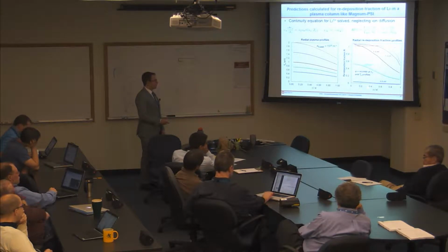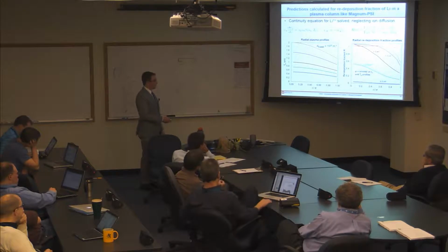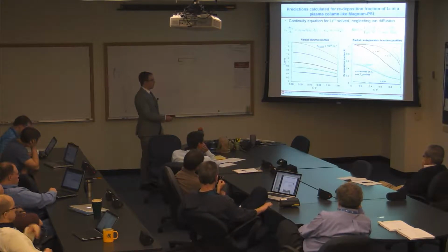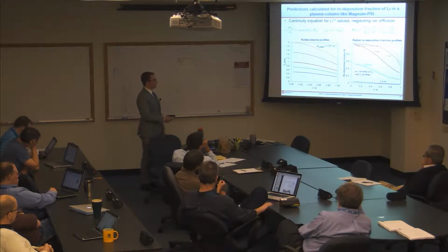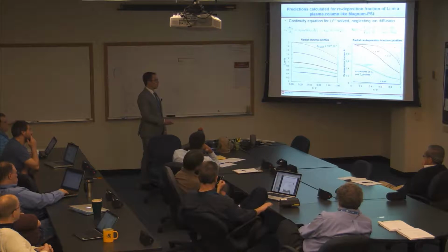And for a temperature of half an eV, you get almost no redeposition. But because the ionization mean free path of lithium decreases so rapidly between 0.5, 0.75, 1 eV, you actually get a very strong increase in the predicted redeposition fraction as a function of temperature. And at 2 eV, you have basically unity redeposition across the surface, actually a bit higher than unity, because some atoms are actually eroding from near the edge of the target and redepositing on the middle.